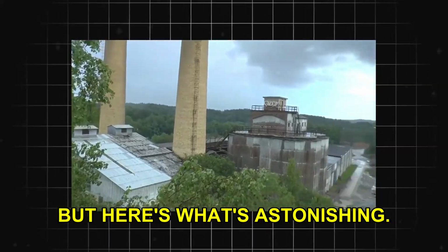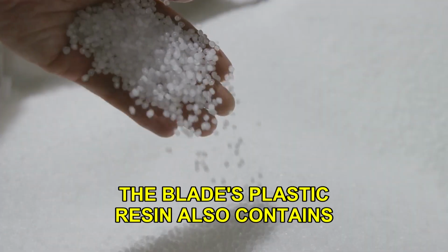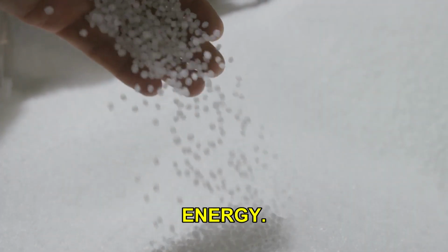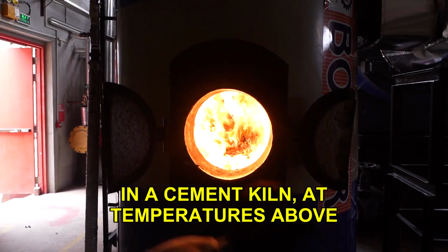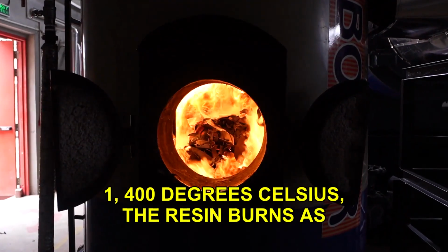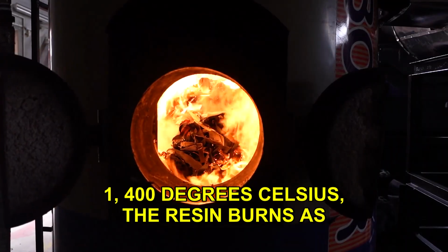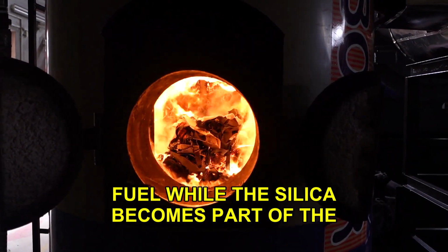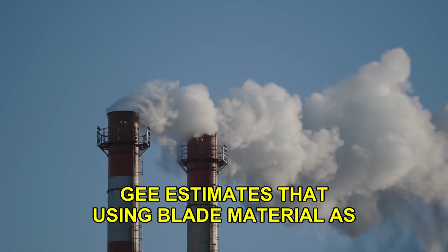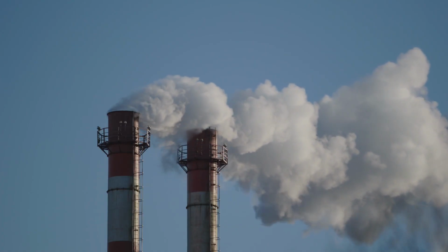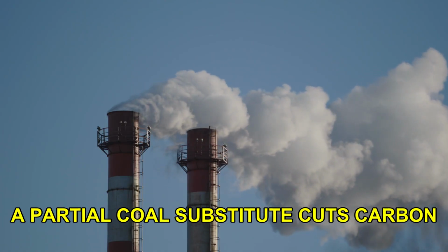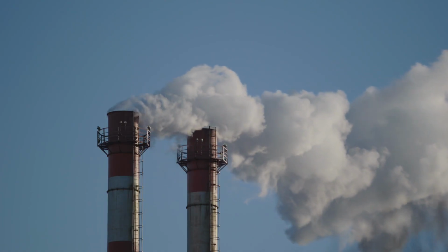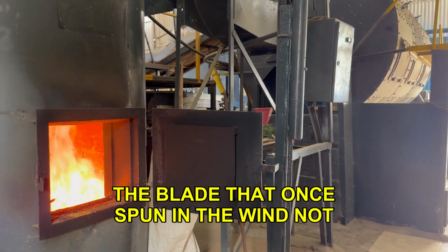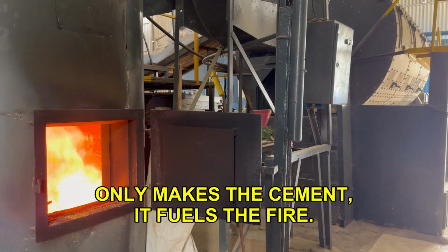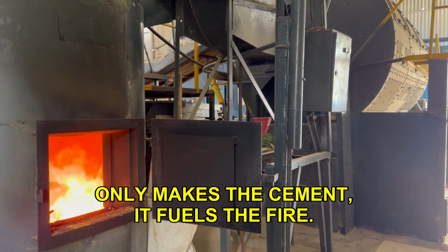But here's what's astonishing. The blade's plastic resin also contains energy. In a cement kiln, at temperatures above 1400 degrees Celsius, the resin burns as fuel while the silica becomes part of the clinker. GE estimates that using blade material as a partial coal substitute cuts carbon emissions by up to 27%. You read that right. The blade that once spun in the wind not only makes the cement, it fuels the fire.